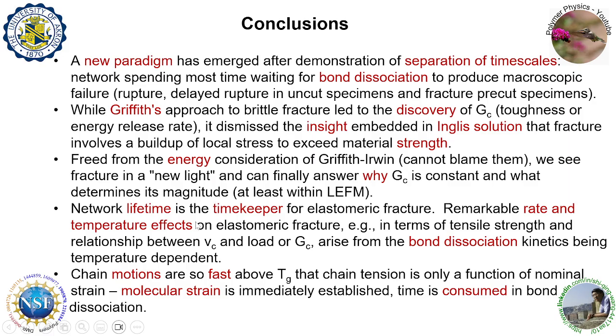So finally, I want to say that the timekeeper in your elastomer is this network lifetime through bond breaking, not polymer relaxation time. So indeed, there were two time scales, except for 70 years we've mistaken the time scale to be that of polymer relaxation rather than this lifetime through bond dissociation. In other words, the motion generally is much, much faster. Most of the time is spent, like Smith did for 7 days, because the tension is not high enough. So he waited for 7 days, boom, break. All the molecular motions are irrelevant, as you know. But yet, they still wait. So that's the conclusion, really.